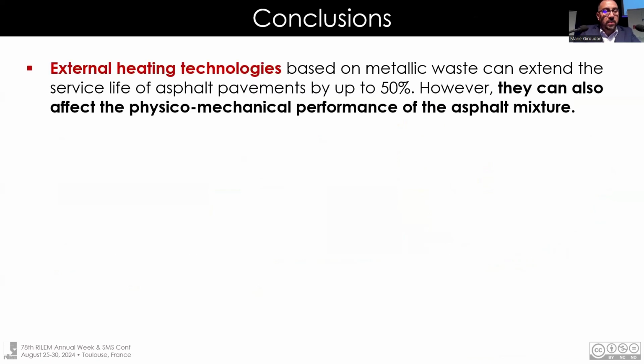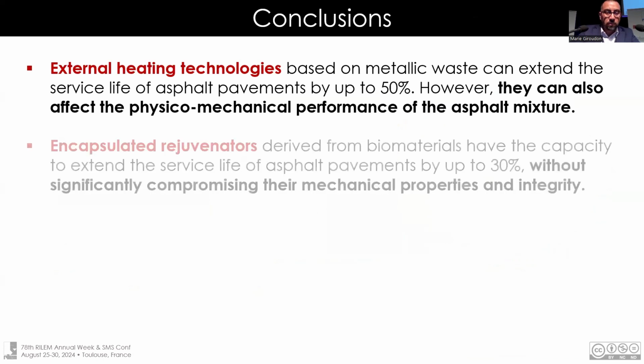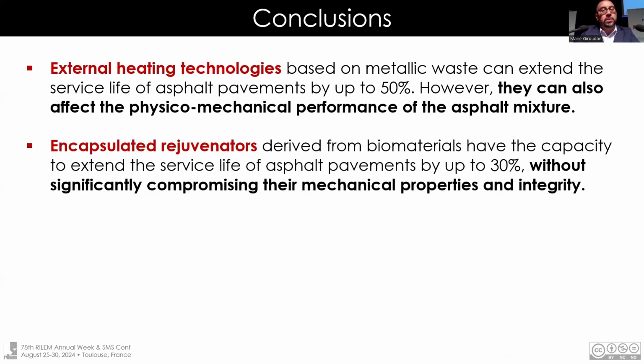In conclusion, I would like to highlight 4 different topics. The first is that external heating technology based on metallic waste can extend the service life of the asphalt pavement by up to 50%. However, this can also affect the physico-mechanical performance of the asphalt mixture. Concerning the encapsulated rejuvenators based on biomaterials, we have the capacity to extend the service life of the asphalt pavement about 30% without affecting the mechanical properties and integrity of the asphalt mixture.